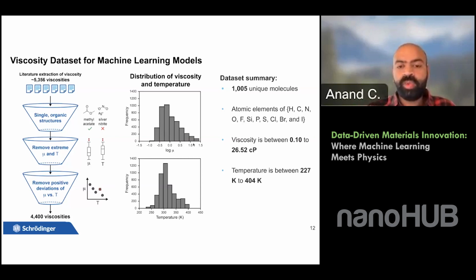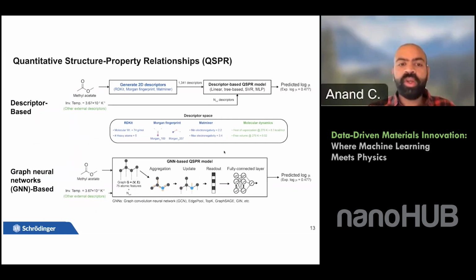So this is the distribution of the viscosity, and this is the distribution of the temperature of the measurements in which the viscosity was made. Overall, we had more than 1,000 unique molecules with viscosity measurements, and the temperature ranges from 227 Kelvin to 404 Kelvin, and the viscosity ranges from 0.1 to 26 centipoise. So the goal is, can we create machine learning models for this particular property as a function of temperature?